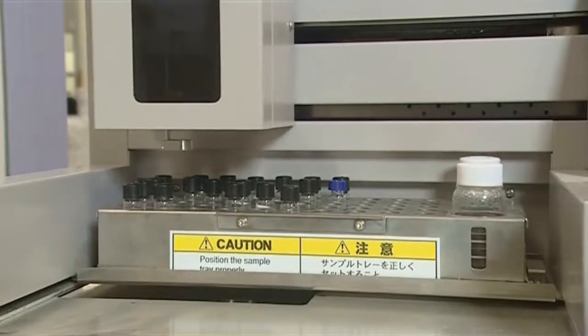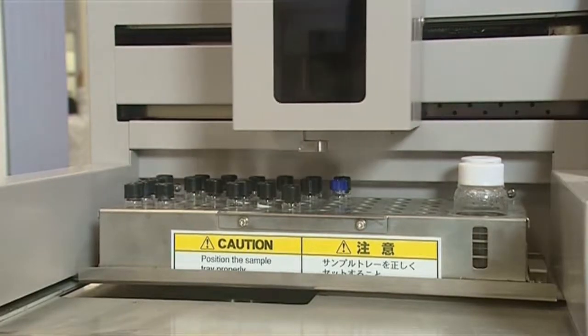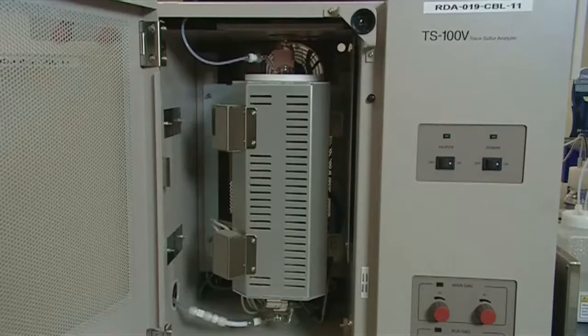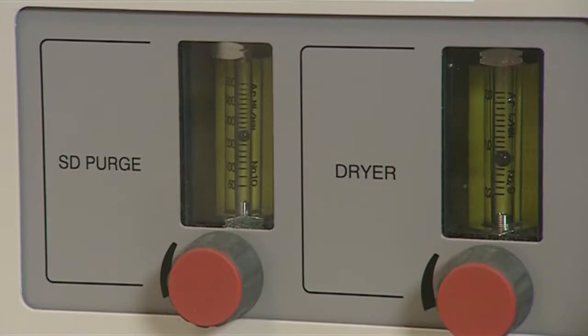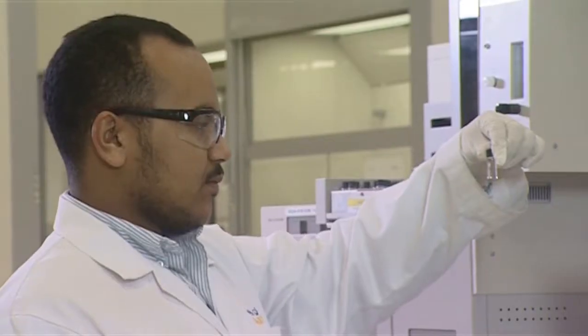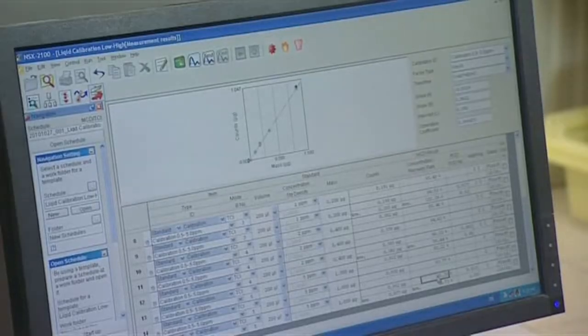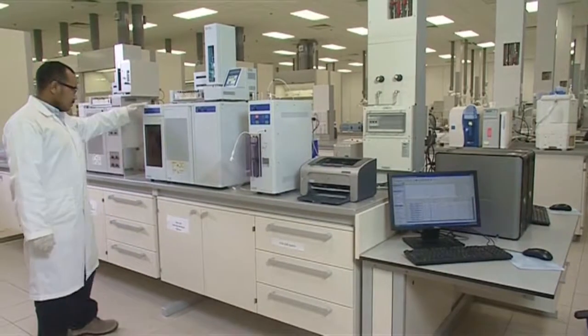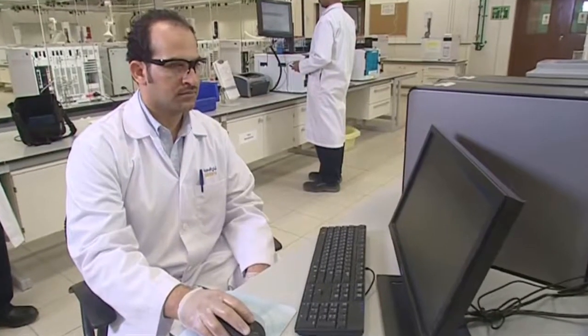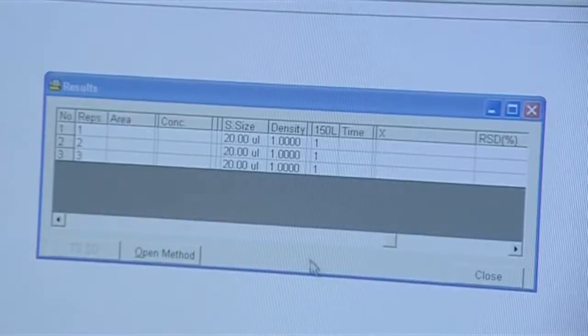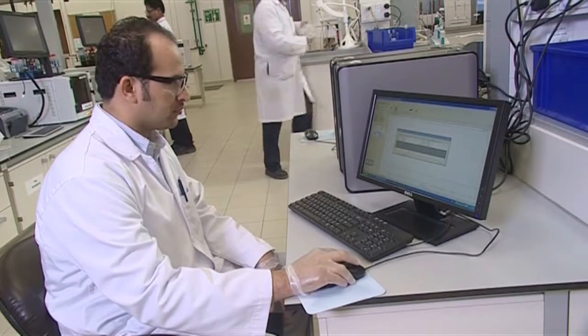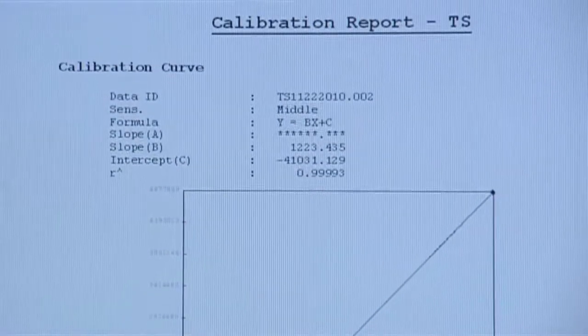The sample is injected into a reaction tube, maintained at a high temperature, 800 to 1000 degrees Celsius, using argon gas for the carrier gas. Sulfur compounds in the sample are broken down by pyrolysis. The total sulfur concentration in the sample is then determined using a calibration curve prepared in advance with a standard solution.